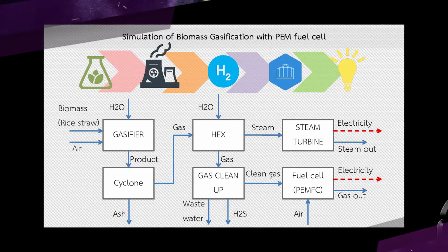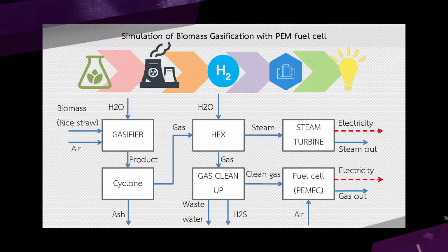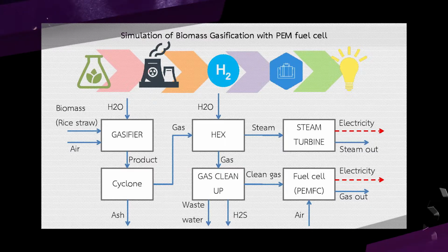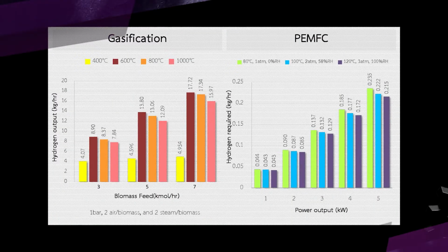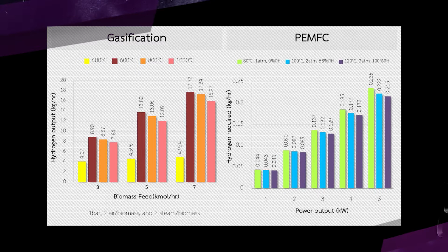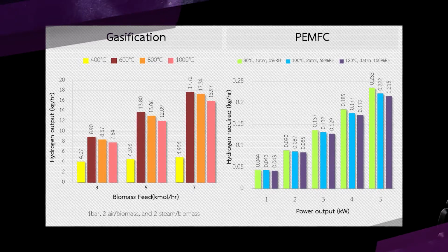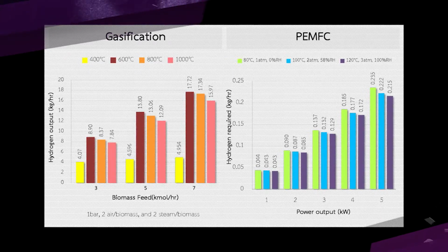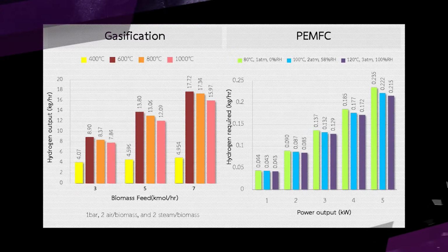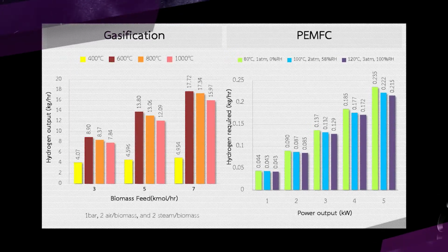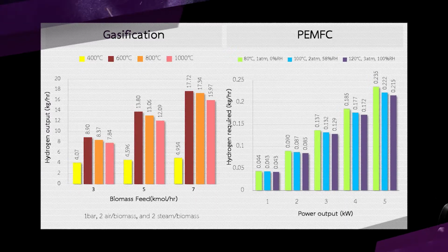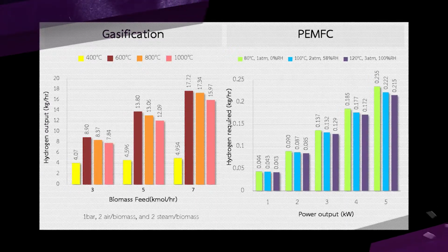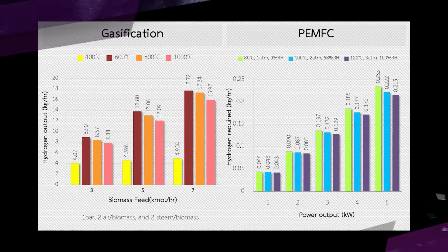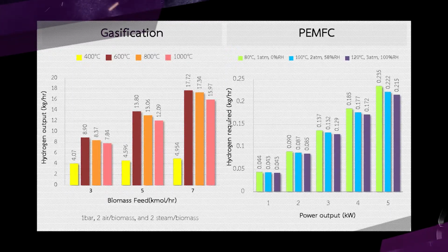The biomass is basically fed into the gasifier to produce hydrogen. The hydrogen is further sent to the PEM fuel cell to produce the electricity. From the result, as the temperature of the gasifier is varied from 400 degrees Celsius to 1000 degrees Celsius, the hydrogen output is rising until it reaches the maximum at a temperature of 600 degrees Celsius, giving the highest amount of hydrogen. Therefore, the best temperature of the gasifier is 600 degrees Celsius for every biomass feed rate.